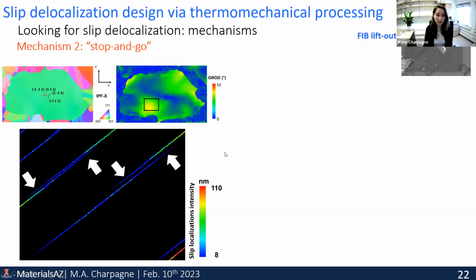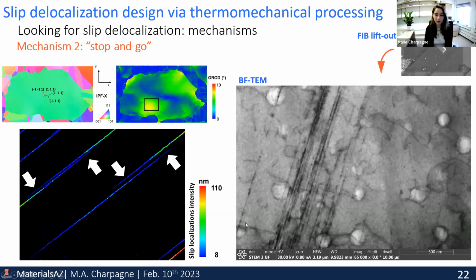And to try and identify the fundamental mechanism behind this, we take a FIB lift-out to see in depth what happens in the bulk of the material, underneath this surface. And we found a lot more dislocation activity than we thought we captured on the DIC maps, meaning that we actually have way more slip bands that contain very, very few dislocations underneath the surface. And the question of what the fundamental mechanism is is still in the process of being answered.